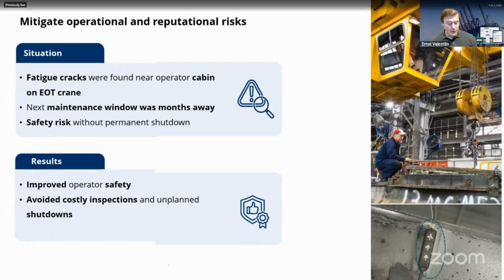In the meantime, to ensure that the crane was still safe to use and the cracks wouldn't really have a lot of structural risk in the meantime, the sensors were brought in and they were put on all of the existing cracks to detect whether or not those cracks were growing and how rapidly they were growing. In this case, because it was only 16 of the sensors, we managed to squeeze the installation into a long shift change. So within 1 or 2 hours, we managed to install the entire system, and after which we were able to report back to this asset owner what was happening there.